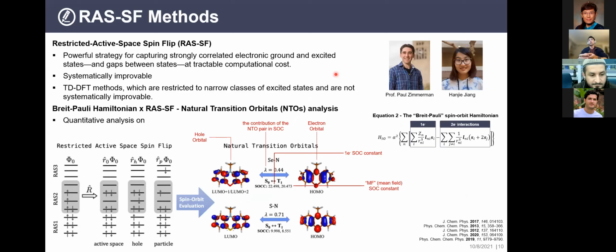At this point, we definitely cannot just stick with a very simple DFT calculation. So we reached out to our collaborator, Professor Zimmerman, and my direct contact, Han Jie. Their group specializes in the so-called restricted active space spin-flip, which is a wave function method that gives a more precise interpretation of the angular momentum effect and the spin-orbit coupling in general, which is a very nice calculation package. And we can get a very accurate representation of what is actually going on over there.